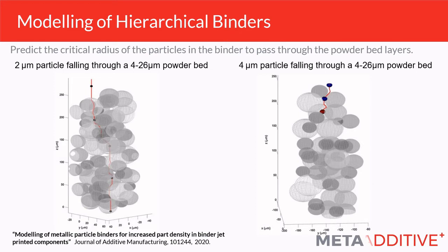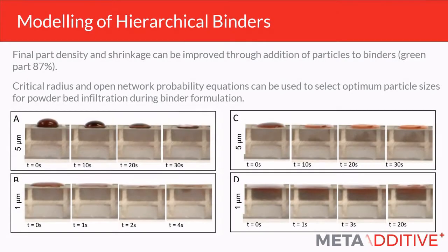The left-hand side is showing one that's at 2 microns in radius, and that can percolate all the way through the powder bed. So it's really about can we use these mathematical models to predict what's the best size fraction and the size range that we need in our binders, so that they will percolate and penetrate that powder bed uniformly and get the best density and shrinkage as a result.